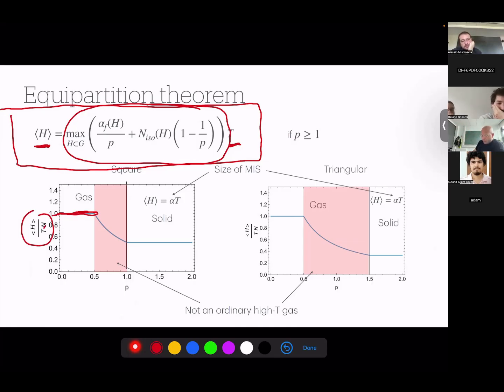But for P even larger than 1/2, you don't have the usual equipartition theorem. Here is the solid phase. But the gas phase for P between 1/2 and 1 is still an unusual gas phase. There are some correlations at very high temperature, right? It's not the usual gas. This is one point that I wanted to stress.